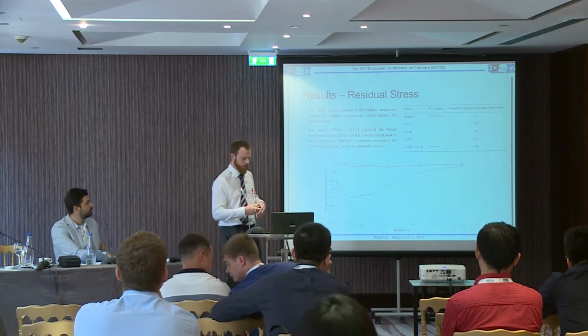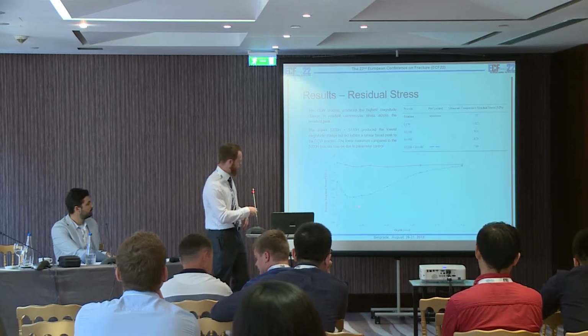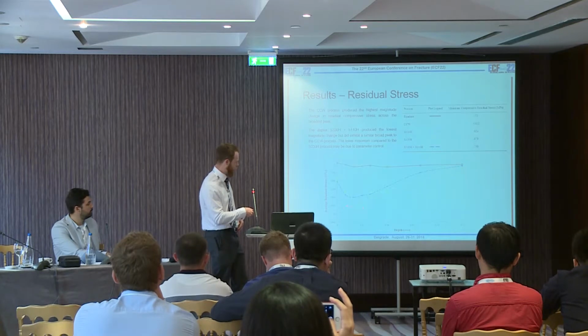So the results for the compressive residual stresses. These colours don't seem to have turned up very well, but the red line across the top, that's our baseline material. We saw the greatest increase in the compressive residual stress for the conditioned cut wire process. So not only did we see the greatest residual stress at approximately minus 1,100 megapascals, we also saw the broadest peak across that range.